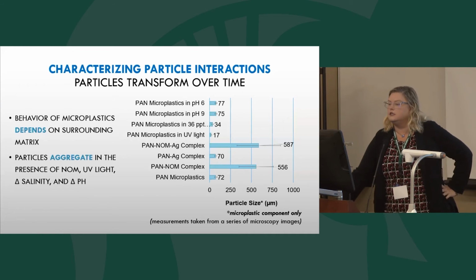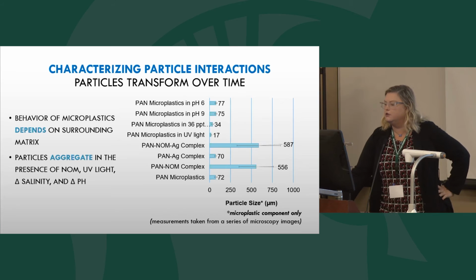The PAN microplastics at the nominal pH have a size of around 80 micrometers. But when you change the pH, it doesn't really change. You put some salinity in it, some salt in it, it decreased. You irradiate it with the solar simulator lamp, it went really small. And then as soon as you complexed the PAN with the natural organic matter and the silver, the particles got really large, presumably because of the natural organic matter. As shown here, the PAN with the natural organic matter by itself has very large particles. But with the PAN and the silver complex by itself, we're still around the same nominal size population as the PAN itself whenever it is in environmentally relevant pHs.